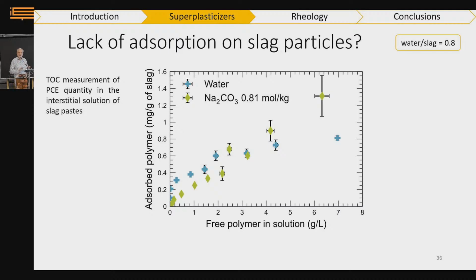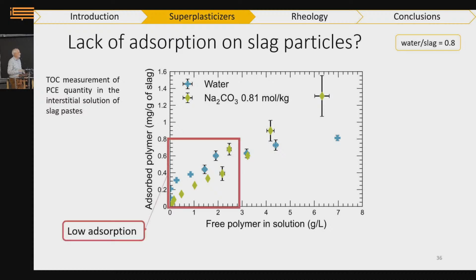So here, something goes on. We don't really know exactly what, but something in presence of sodium carbonate prevents the polymer, or doesn't fully prevent, but reduces the ability of the polymer to adsorb on the surface. So the adsorption is lowered.